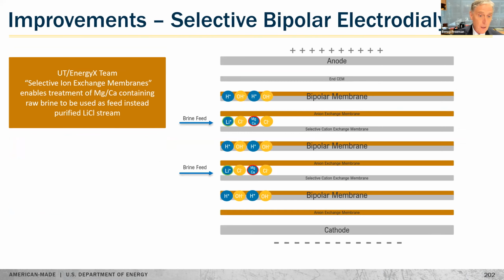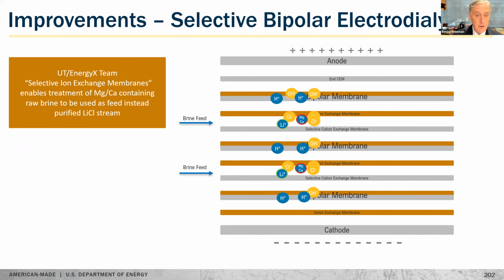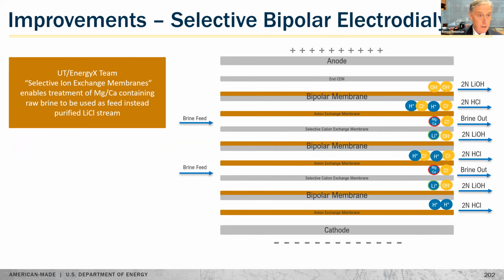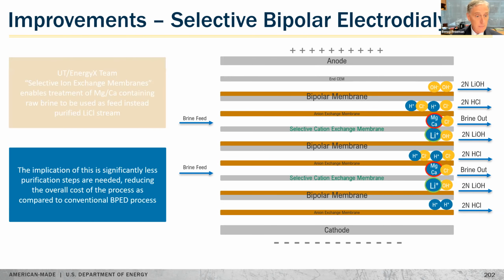And with the selective cation exchange membrane, the magnesium and calcium are rejected and never get into contact with the hydroxide solution. And so now when we take lithium across that selective cation exchange membrane, we make lithium hydroxide, we leave the magnesium and calcium behind. If they get into that lithium hydroxide stream, they will foul the membranes. They'll plate out as mineral scale. And so we avoid that with the selective cation exchange membranes. And so as a result of this, we can work with significantly less pure brine feeds to this process.